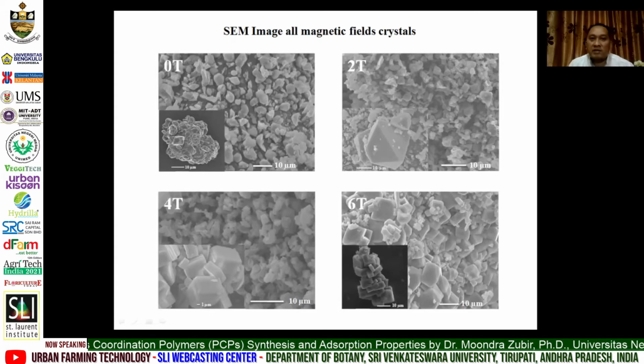And this is the SEM image for all magnetic field crystals. You can see the morphology of the crystal change from 0 Tesla, 2 Tesla, 4 Tesla, and 6 Tesla. Even though 2 Tesla and 4 Tesla look like similar morphology, 0 Tesla and 6 Tesla look like a significant change of the morphology. It's supported by the XRD pattern that 2 Tesla and 4 Tesla have the same intensity change for XRD patterns, also inducing a slight change of the morphology before the change from 0 Tesla to 6 Tesla.